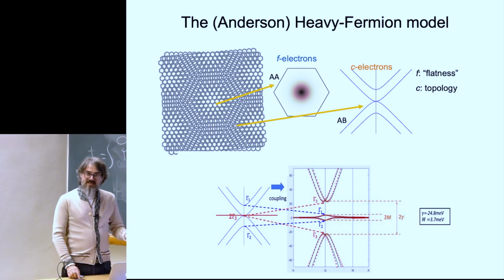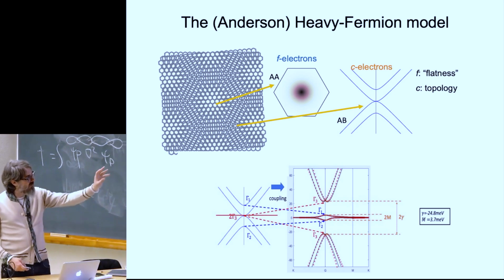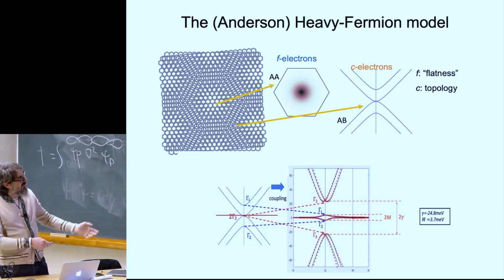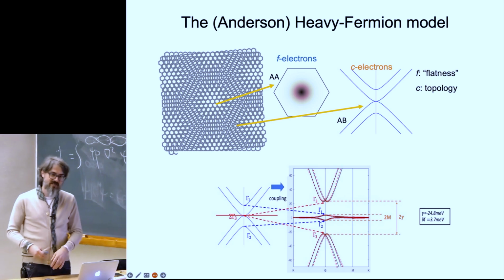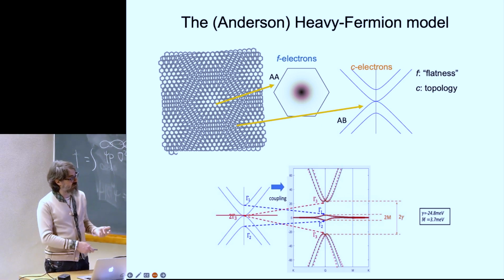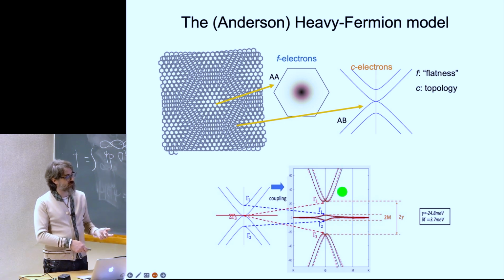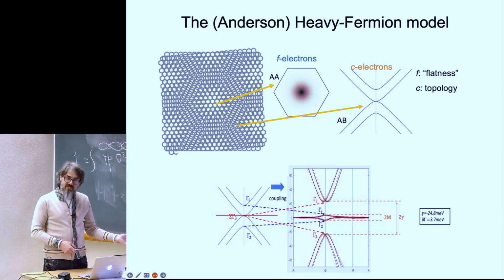So why do we make this? Why did I say that we're going to make these flat electrons, conductive electrons? This is really just a basis change. You see, at least at low energies, the Coulomb interaction is of the order 30, 40, 50 milli-electron volts. It can only get you from here to here within this energy range. I'm not going to match things at high energies. The experiment is not at high energies. But this is a good unitary transformation at low energies. It's actually almost perfect at low energies.